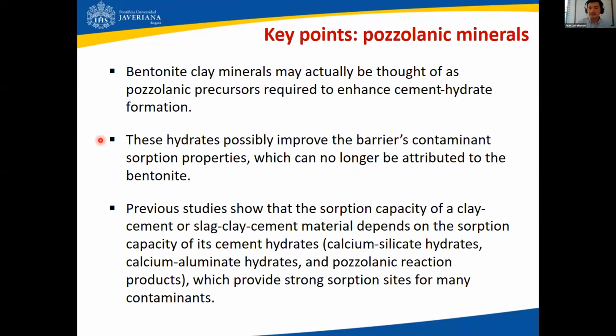These hydrates, the pozzolanic hydrates, are known to improve, or may possibly improve, some of the barrier's contaminant sorption properties, which, like I said before, can no longer be attributed to the bentonite because the bentonite disappears quickly due to the reasons I explained before.